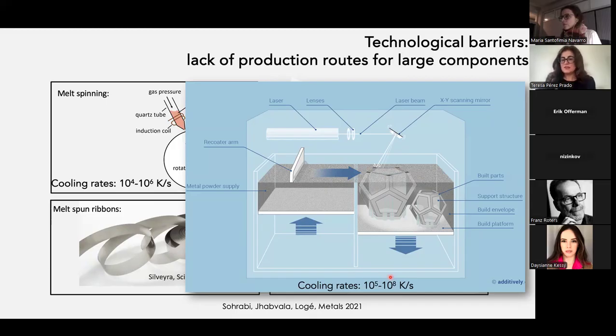And then, so this is one thing. We could in situ potentially make these amorphous materials. And then the second feature that is very useful for us is this freedom of design. We said that a third source of losses was related to the design of the component, the impossibility to make these complex geometries. So in theory, with additive manufacturing, laser powder bed fusion in this case, we could simultaneously and potentially make this fully amorphous component with a complex geometry.